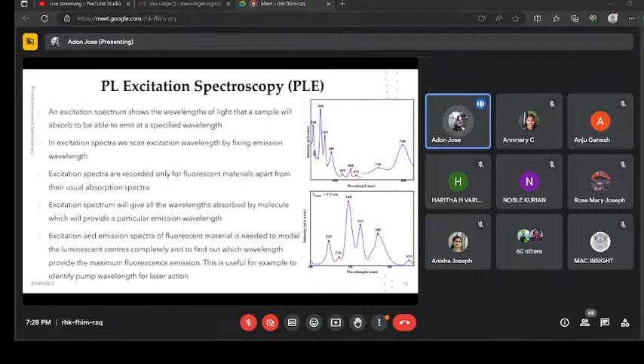We have maybe studied absorption spectroscopy in the previous classes. There are certain similarities between absorption spectra and excitation spectra. Usually, the absorption spectrum is a general scan, and it can be done over a range of around 300 to 2000 nanometers, depending on the device that you are using. Whereas an excitation spectrum can only be recorded with a fixed emission wavelength. That means for absorption spectra, we can simply record the absorbance by varying the electromagnetic radiation falling on the sample. Whereas whenever we need to record the excitation spectra, the first factor we need to know is the emission wavelength.